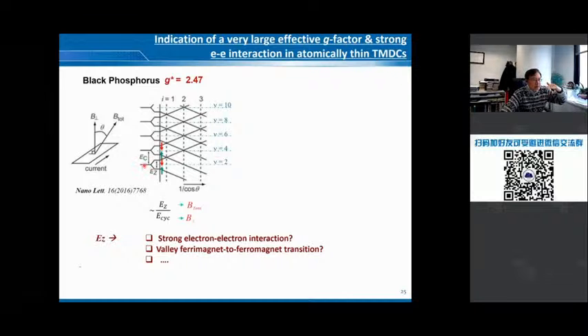But if I tilt the magnetic field or tilt the sample, this ratio is changed. Now first, the Zeeman energy is assumed unchanged and independent of the B field tilting. It's determined by the total magnetic field. But the cyclotron energy at the Landau level formed in the planes depends on the B component, the magnetic field component perpendicular to this. So once I tilt, these two energy gaps will cross, and eventually I can determine the angle and determine the ratio, and then I can determine the G factor.